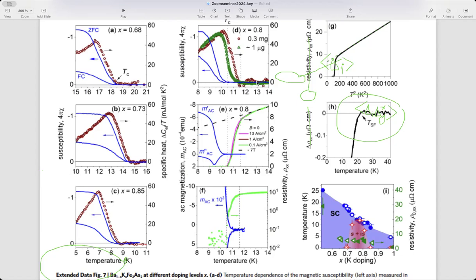There is dead zero diamagnetic susceptibility, but the specific heat jump fully develops. And this is a reference sample at other doping. So the usual picture of a phase transition is where specific heat correlates with the onset of diamagnetism. And here, since this is a time reversal symmetry breaking electron quadrupling condensate, order only in relative degrees of freedom, it has no Meissner effect, no diamagnetism.